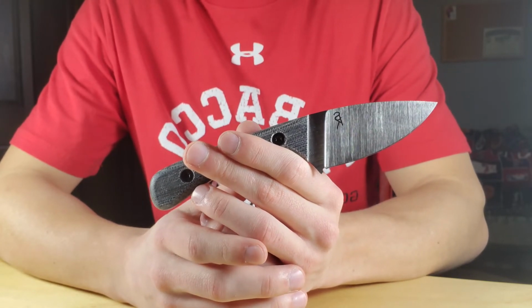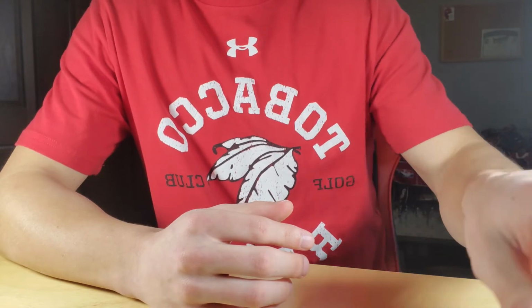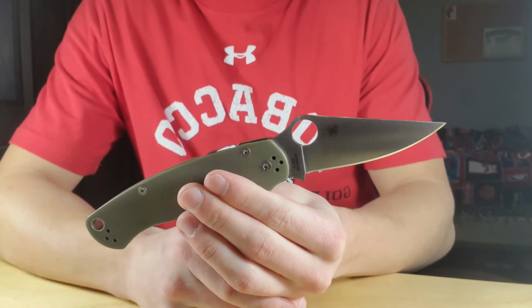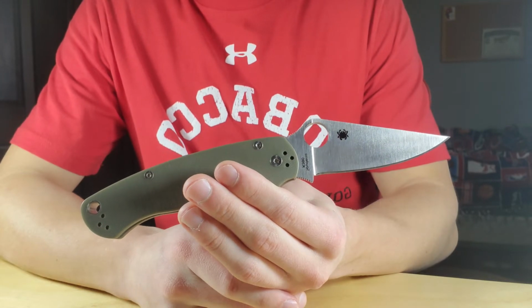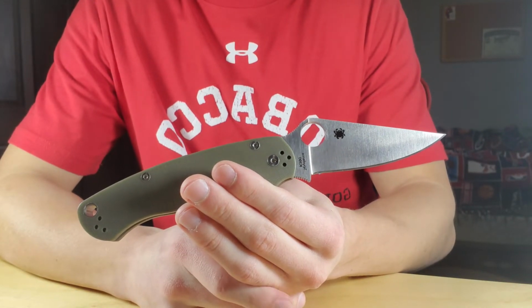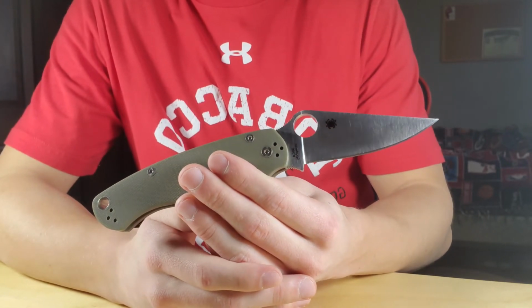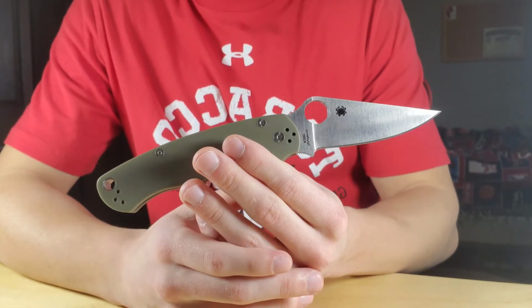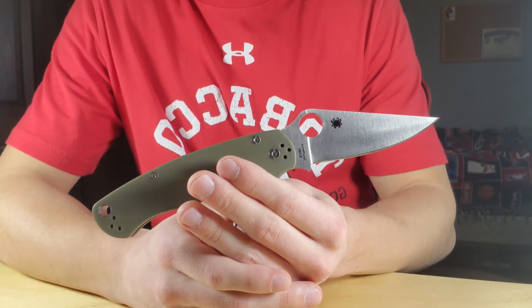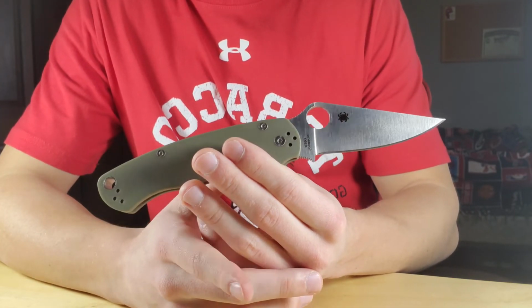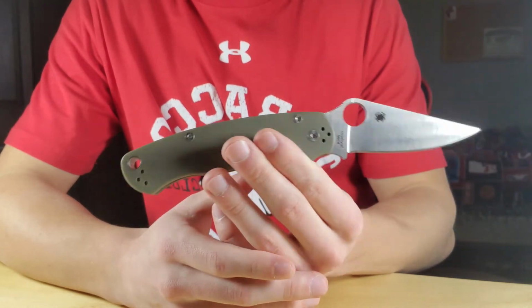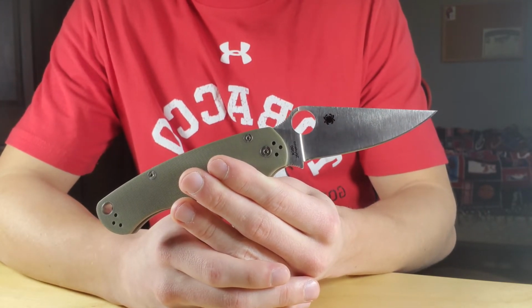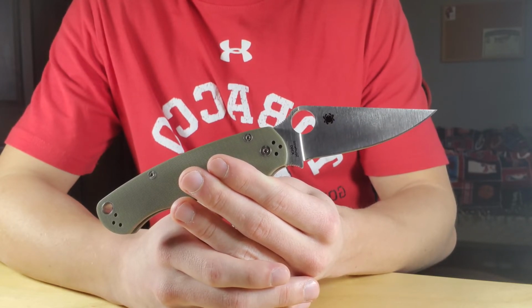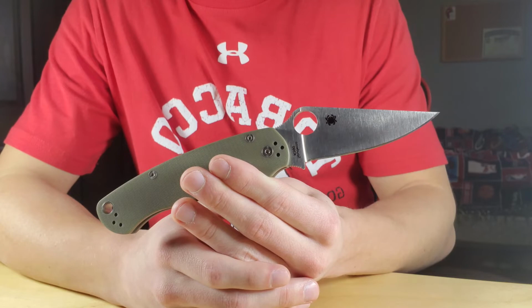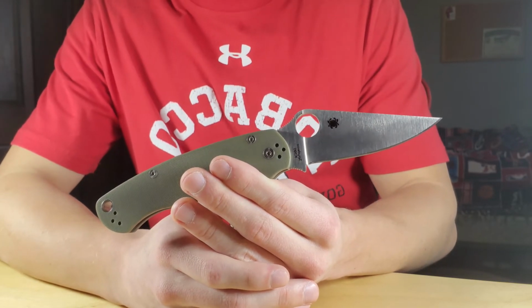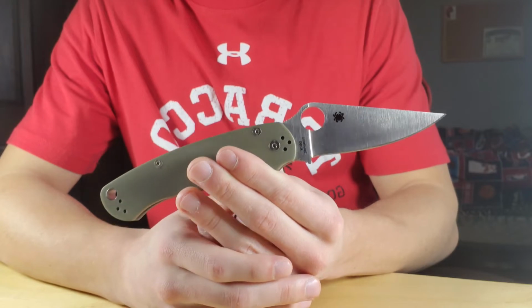So extremely impressed with this, but let's compare that to the PM2 in K390. Same steel, obviously, but this one is at 63 to 64, which is what this whole run seems to be coming in at. I'm just assuming this is 63 to 64 at 18 degrees per side, and this is sitting at 28 thousandths behind the edge. When we tested this last time with the same progression that we used on that Shark, it cut 480.38 feet. So a pretty significant difference.